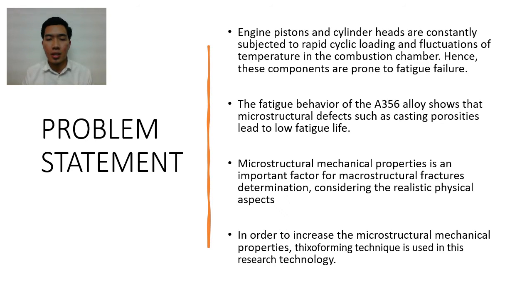For the problem statement, the engine piston and cylinder head are constantly subjected to rapid cyclic loading and fluctuation of temperature in the combustion chamber, such as in pistons, diesel engines, and compressors. Hence, these components are prone to fatigue failure. The fatigue behavior of the A356 alloy shows that microstructural defects such as casting porosity lead to low fatigue life. These microstructural mechanical properties are an important factor in determining microstructural fractures, considering the realistic physical conditions. In order to improve the microstructural mechanical properties, the Thixoforming technique is used in this research.